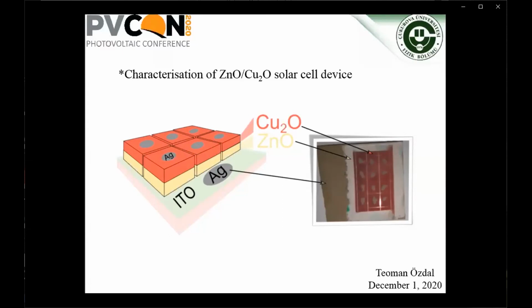By dividing the cell surface into islands, we can obtain individual IV characteristics from different parts of the device. Here we can see 12 different islands, separated, and they have common back contact here, and individual top contacts, silver contacts here.